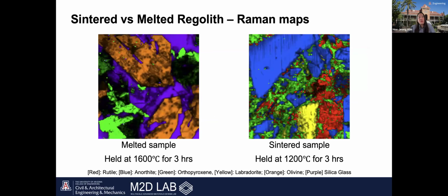And the melted sample shows clear signs of recrystallization and a loss of the original powder morphology, meaning the individual particles had fully fused together into a dense glassy structure. In contrast, the sintered sample retains its distinct particle shapes, with the particles bonded together at their contact points while still maintaining a visible granular structure. And these results show how processing temperature strongly influences the microstructure, with sintering preserving particle features, and melting producing a more homogeneous and fused material.